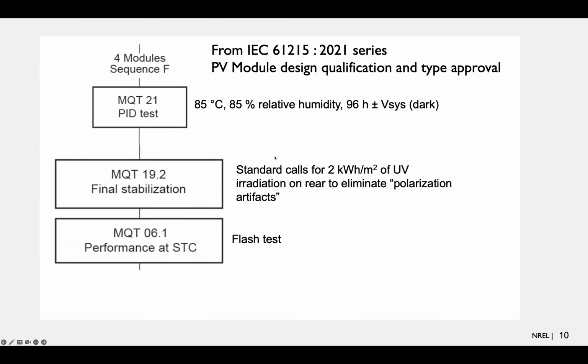The 61215 2021 series of the PV module design qualification and type approval involves a PID test, which is 85 degrees C, 85% relative humidity, 96 hours with system voltage in the dark, some modules in positive voltage, some modules in negative voltage, to see their PID susceptibility. Then a final stabilization is called for, and that calls for specifically 2 kilowatt hours per meter squared of UV irradiation on the rear to eliminate polarization, so-called artifacts.